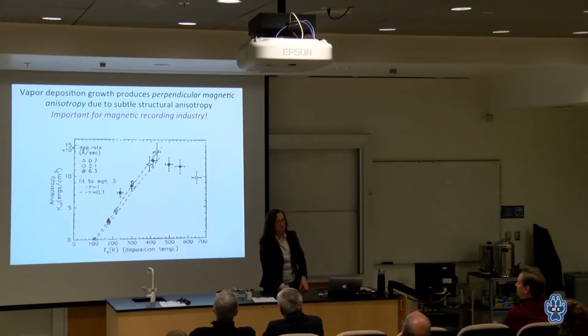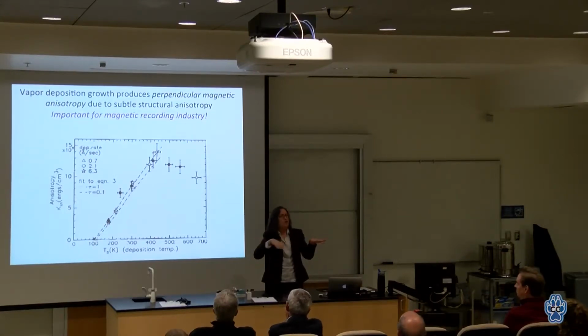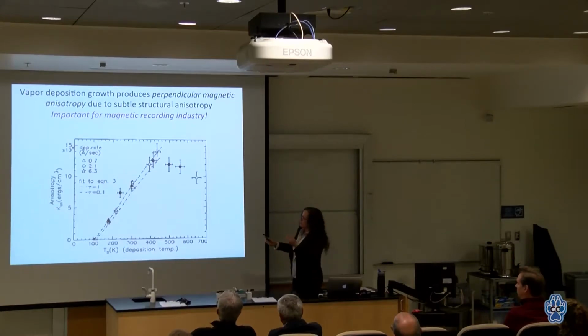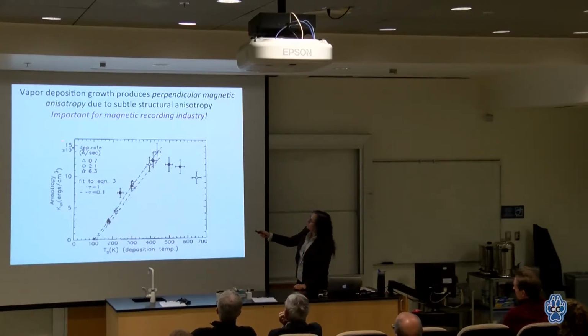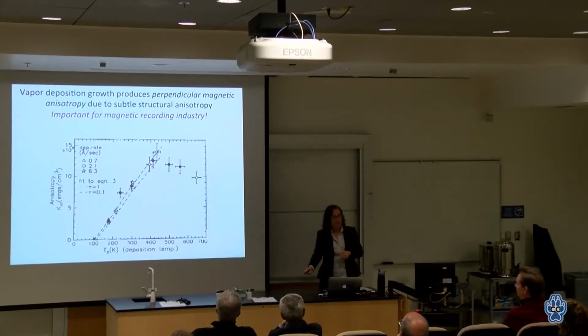So it isn't a memory in the sense of, if I showered them down, they get stuck in a pile of wet sand or something like that. This is that the more mobility I give it, the more anisotropic it becomes. So this is all connected to minimization of surface energy in a way. And the end result is, these numbers don't mean anything to you, nor should they, but this is actually quite a lot of magnetic anisotropy.